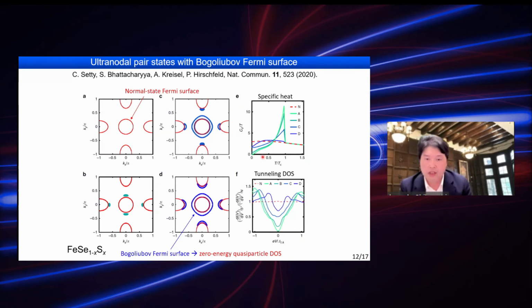So from the specific heat data and tunneling density of states, we have shown that we have very large residual zero energy density of states in the tetragonal side of iron selenium sulfur, which shows very good consistency with the theory showing this Bogoliubov Fermi surface.